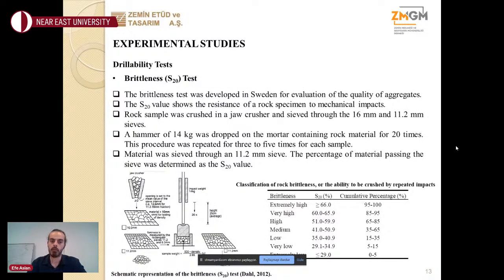The second test we need to conduct to obtain the drilling rate index is the brittleness test. It was also developed in Sweden for evaluation of the quality of aggregates. The S sub 20 values show the resistance of a rock specimen to mechanical impacts. A rock sample was crushed in a jaw crusher and sieved through the 16 millimeter and 11.2 millimeter sieves. A hammer of 14 kilograms was dropped on the mortar containing rock material 20 times. This procedure was repeated 3 to 5 times for each sample. Material was sieved through an 11.2 millimeter sieve. The percentage of material passing the sieve was determined as the S sub 20 value. Again, on the left-hand side, you can see the schematic representation of the test. On the right-hand side, you can see the classification of the rock brittleness values.